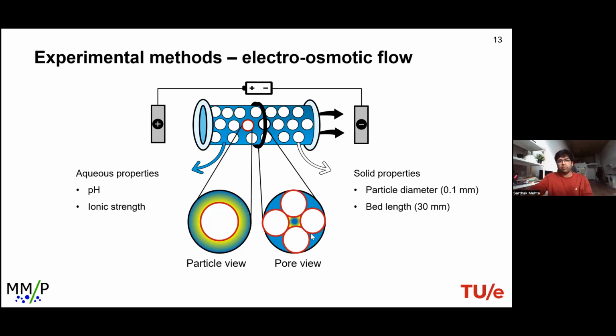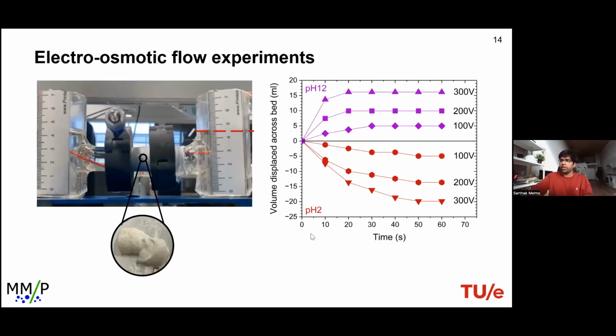We have made some modifications to the initial setup, as you can see here. On the right, you can see the setup modified with two measuring cylinders on each side to measure the amount of water volume displaced when an electric field was applied.